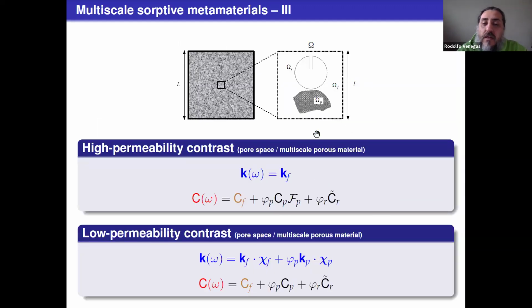So if we consider high permeability contrast between the pore space, here in omega F, and the inclusion of multiscale porous material, then the permeability of the medium is determined by the permeability of the pores. And the compressibility will have a contribution coming from the pores, from the multiscale porous materials, and this apparent compressibility that comes from the resonators. For the case of low permeability contrast, the permeability will have a contribution coming from the pore space and the permeability of the multiscale porous material, with two tensors that are geometric and can be calculated from the solutions of conduction problems. And then the difference for the compressibility is that now Fp, this pressure diffusion function, will become 1, and the rest is identical.